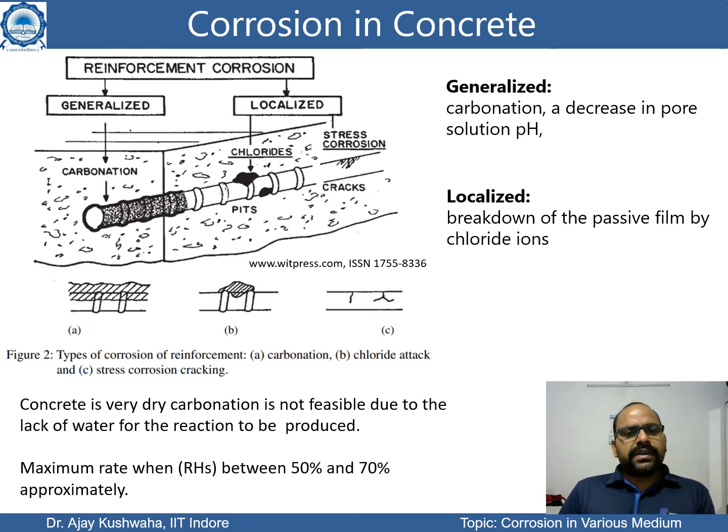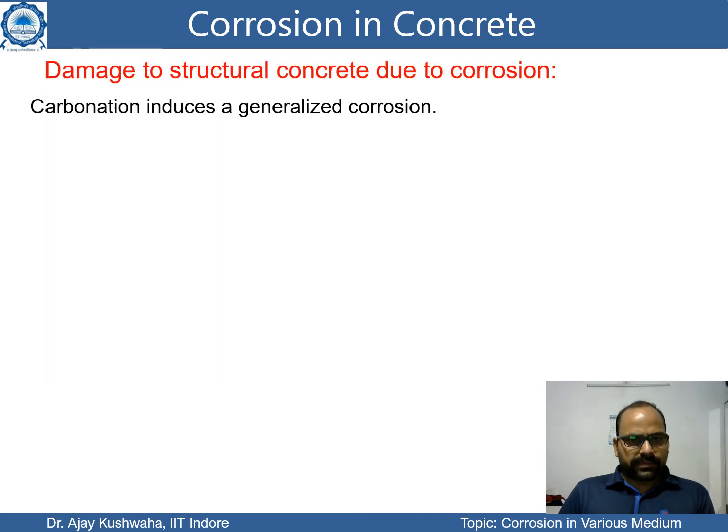If concrete is very dry, carbonation is not feasible due to the lack of water for the reaction to be produced. So if we are having a very dry concrete structure, then the carbonation process is not so easily possible. But if it is having a very high content of water, means if relative humidity reaches the range of 50% to 70%, then there is a chance to have a generalized or carbonation reaction.